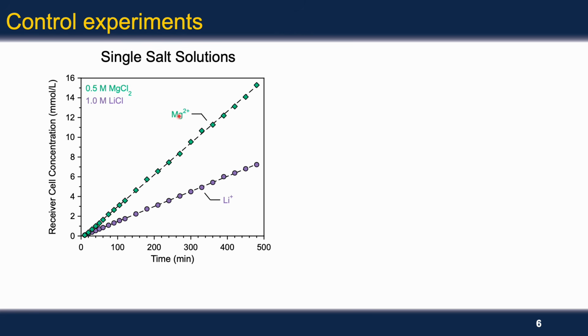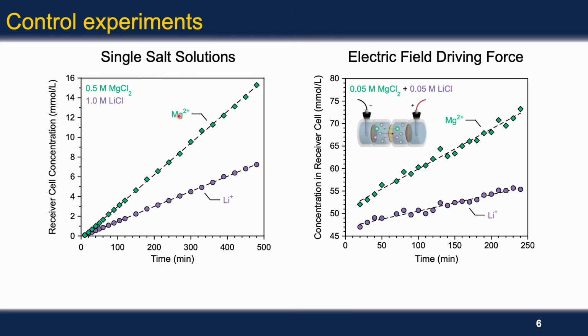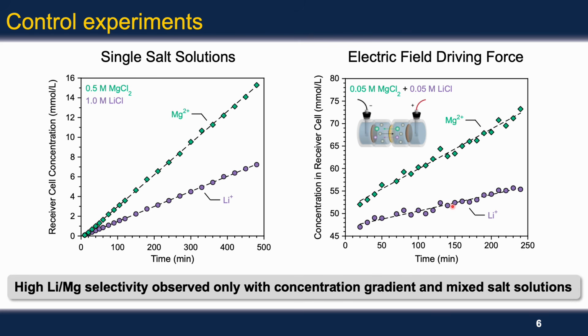We also did some control experiments with electric field driven transport, and also in this case we found that magnesium ions permeate faster than lithium ions. And so our previous observation means that the high lithium-magnesium selectivity is only observed when you have a concentration gradient and also mixed salt solutions.